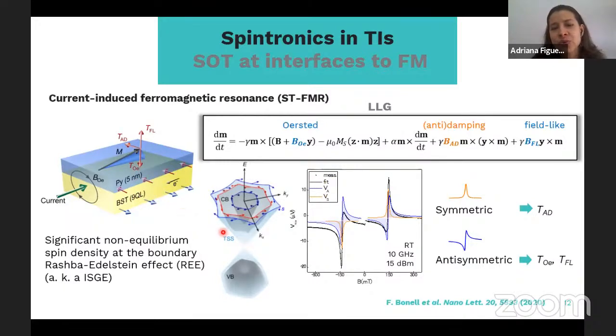And that effect is a consequence of the spin texture that you have in the electronic band of the TI, because of the spin texture of the topological surface state. Sorry. And then those torques can be, of course, studied by spin torque FMR. You analyze the signal that you get with this ferromagnetic resonance, and you have different contributions, and you analyze what kind of contributions.